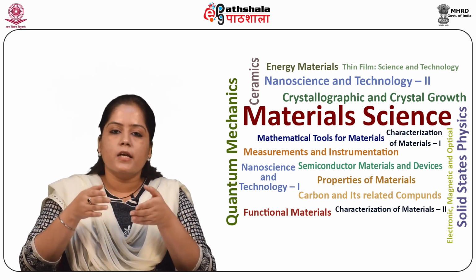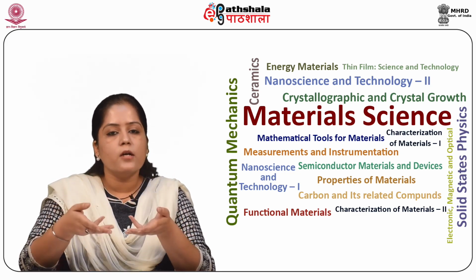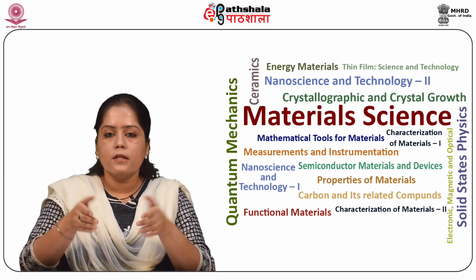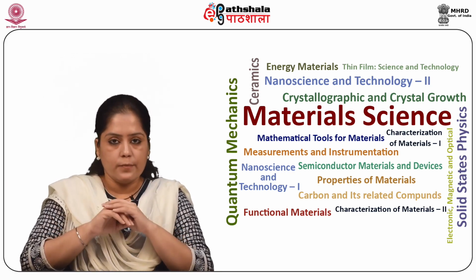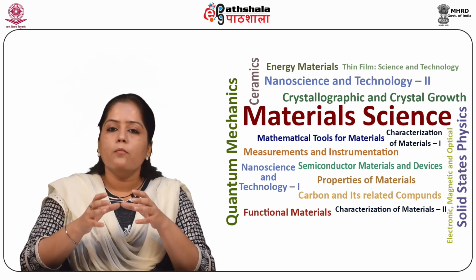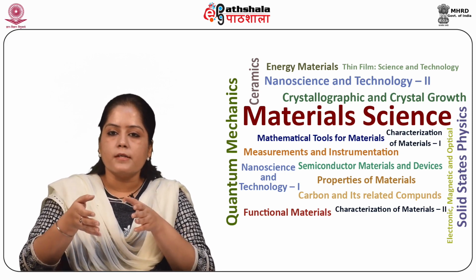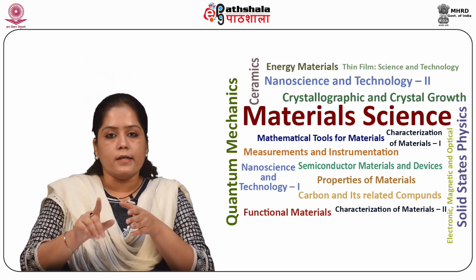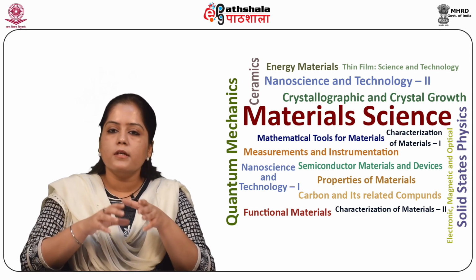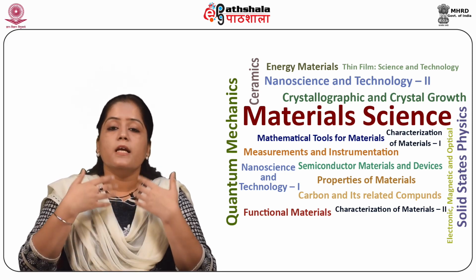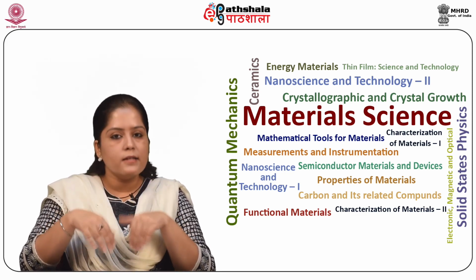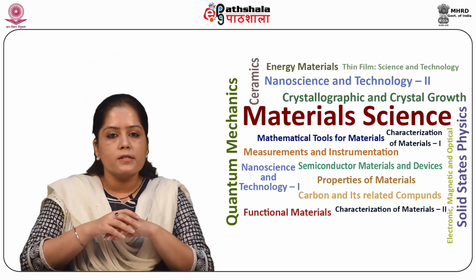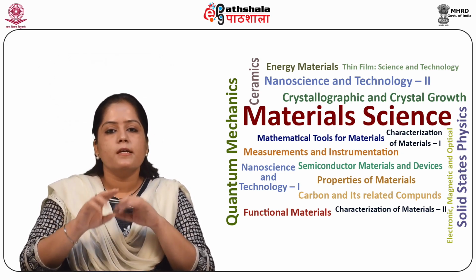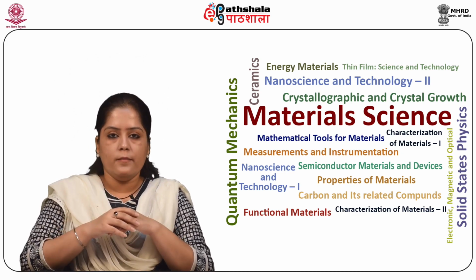Like Cijkl, there are 21 compliances for a crystal with no symmetry. So now, by replacing a pair of indices by a single index according to certain convention, the elastic constants and the compliance are expressed using two indices, say Cmn.